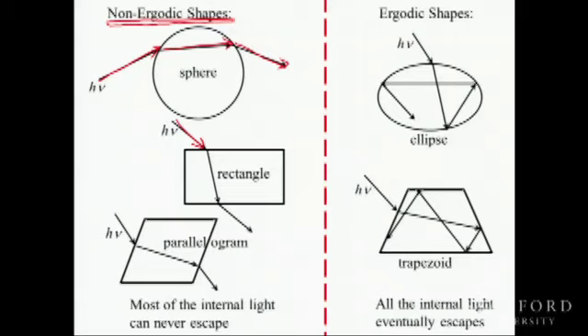The oval. Well, the oval is different enough from the sphere that the oval allows light to be trapped. And once it's trapped, you get this very big factor, this 4n squared factor. The trapezoid likewise. So here there's a dashed red line, and the reason for the dashed red is that these are two different worlds.